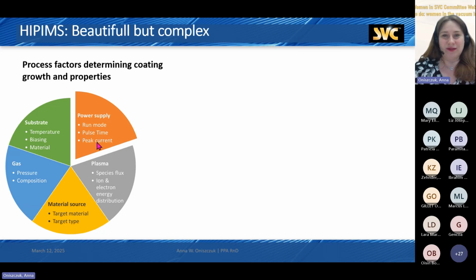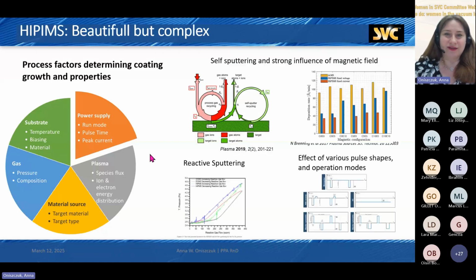When it comes to HIPIMS, there are quite a few other things that you have to think of. For example, there is a big influence from magnetic fields that will lead to self-sputtering. And within reactive sputtering, you have to be a bit more careful than in the case of DC, because, as I showed, there is more dissociation. So you have to know what you're doing. You can control it very well, but you need to take into account that you have much more reactive processes.